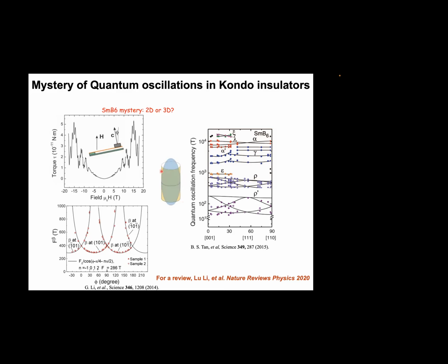No, the reason is if you look at this cylinder, I still always have this smallest cut when the field is exactly parallel to the primary axis of that cylinder. That minimum cut is just this belly. Ah, okay. And then when it goes up to infinity. Right, but you're exactly right. If I have a field 90 degrees away, I would see divergence of orbit sizes, but my oscillation amplitude would quickly diminish because that very first orbit size is too large, and there's not much field really projecting into the effective field. So we quickly diminish. In other words, that's why our error bar is getting bigger and bigger, because the oscillation amplitude is getting smaller and smaller as we go with the field along this axis.